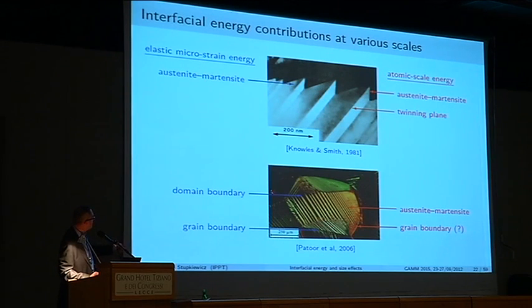Okay, so if you take a bigger look at other microstructures, so this you have already seen, but if you look, for instance, at the grain in a polycrystal, you can also have direct austenite martensite interfaces here between the untwinned plates. In this material, this is copper, aluminium, beryllium, there is no twinning, but there are stacking faults on the other hand. One could also consider that fact, but we will not talk about it. And then you have grain boundary, which has some energy, but on the other hand, the grain boundaries, they don't evolve. So we do not consider the changes in the grain boundary energy in our approach. If one has an idea how to do it, of course, it can be included.